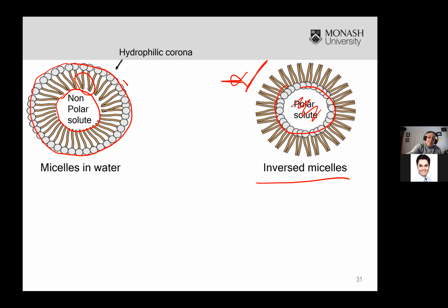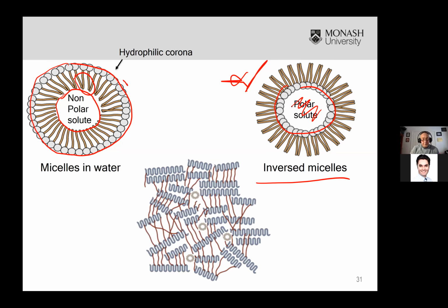And this can be a little bit detrimental to our geomembrane. Why? Because this change in micelle aggregation might facilitate the migration of PFAS solutions through these amorphous zones that we have identified as possibly the weakest link in our polyethylene. And of course, this will be a function of the degree of crystallization, cross-linking, and so forth.